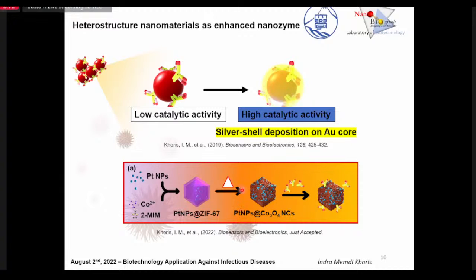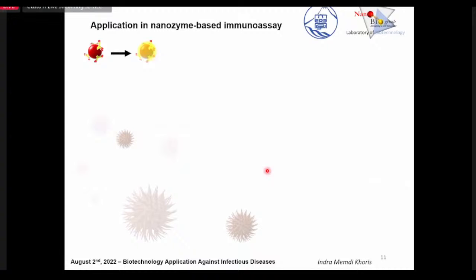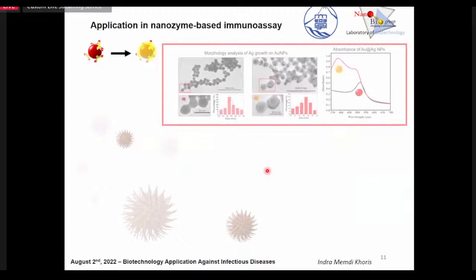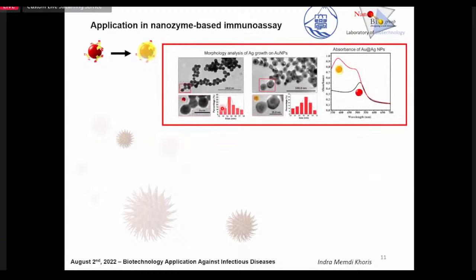And the second one, I will also introduce our recent work on a heterostructure using platinum nanoparticles and the nanocage using MOF, metal oxide nanocage. So the first one, a short introduction of the application in a nanozyme using the heterostructure of gold and silver. We can see here that gold is initially there, then we coat silver on the surface of